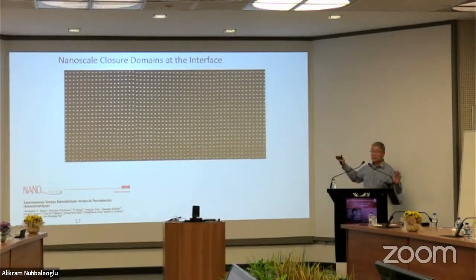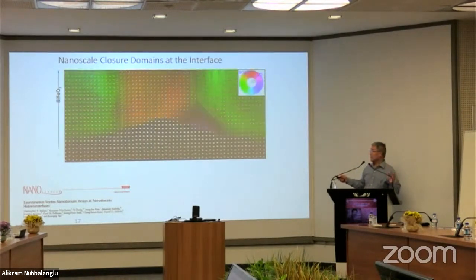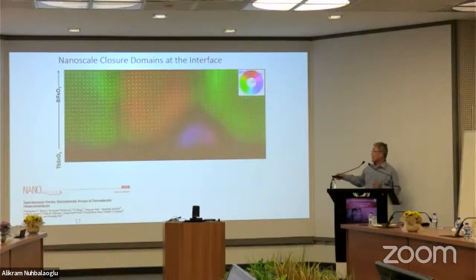Just look at it, you don't see much. But if you use the method developed by Chris and William, you can see the dipole moment from each unit cell. Now you see the polarization is changing from this direction to that direction. It's not a vertical, like a 90-degree rotation. But remember, polarization is not exactly in plane. It's about 45 degrees away. So the angle in 3 dimensions is 109 degrees. So this is a 109 degree domain wall.